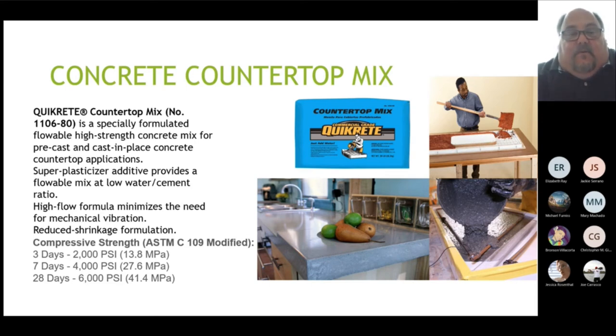One thing you want to make sure when you're using any concrete countertop mix is you want to make sure it's not moving. There's no vibration around it. There's no bumping into it or anything for at least 24 hours before and after you pour. You break the molds loose at about 18 hours. After 18 hours, you can take this stuff and you can add color to it. You can swirl it with color if you want. You can add marble chips. You can add glass chips. You can do all those fun things you do.